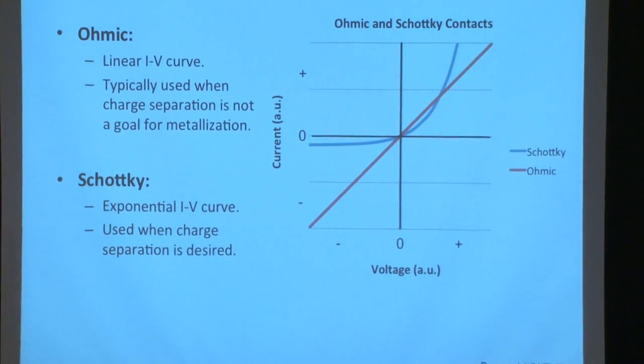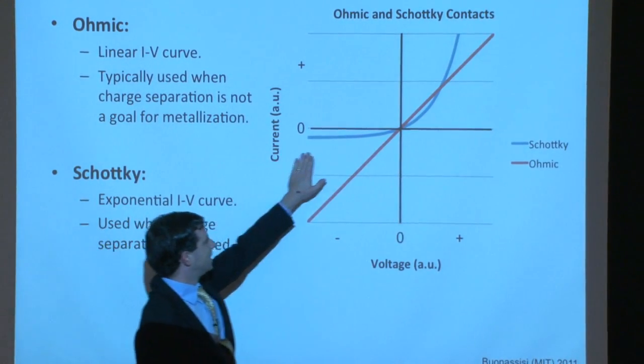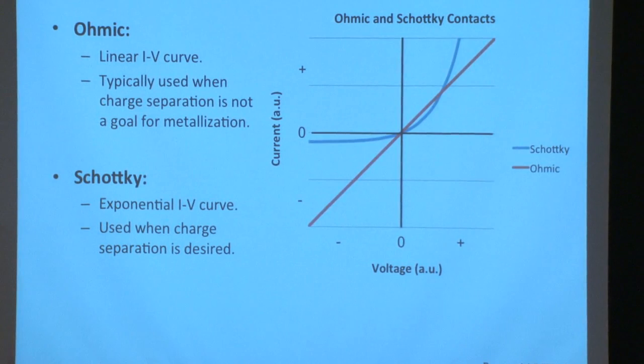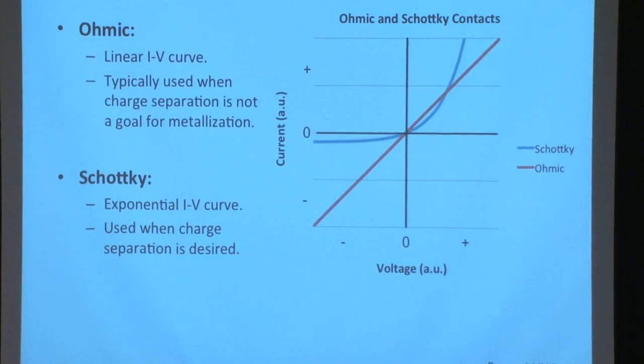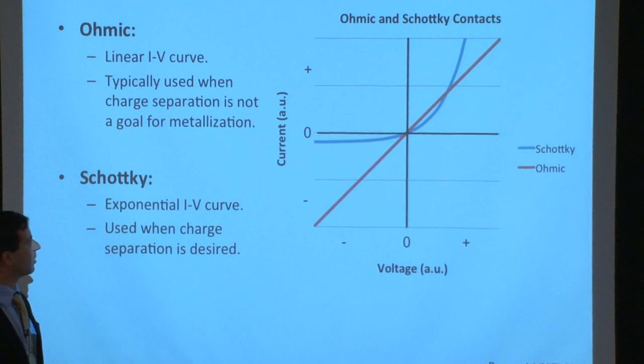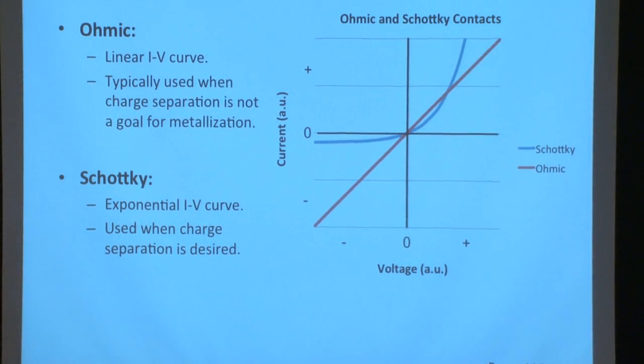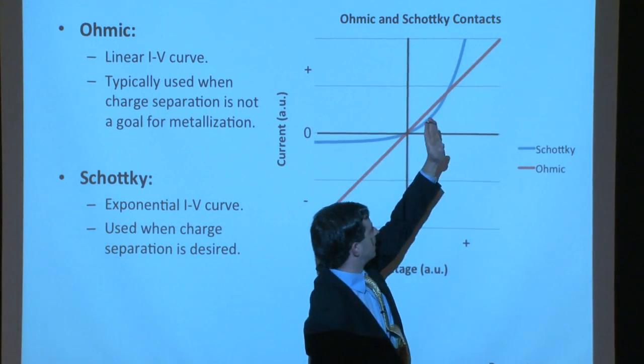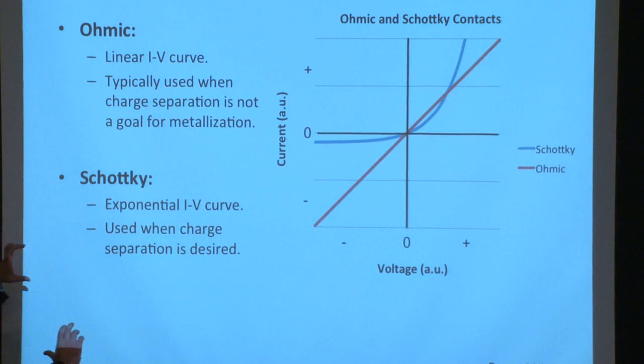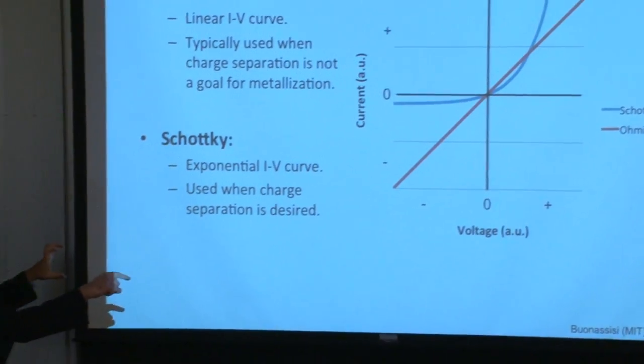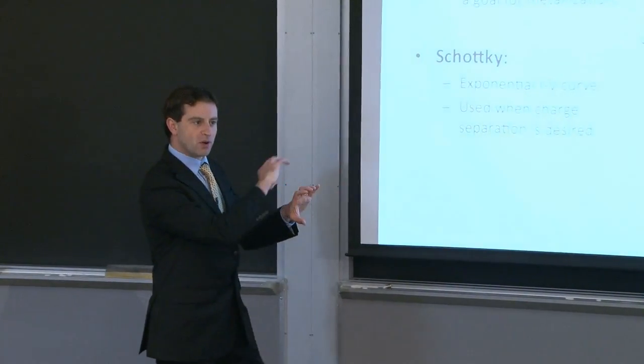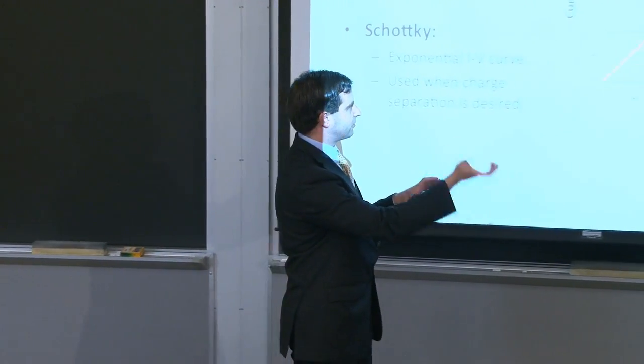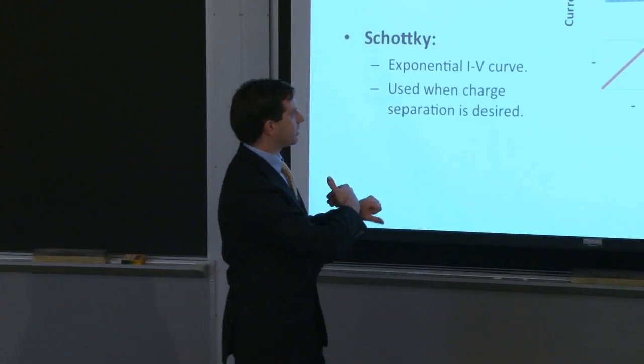A Schottky contact, on the other hand, follows this beautiful exponential curve that we've come to know and love from our ideal diode equation. As a matter of fact, it follows that same expression rather nicely. There's an exponential relation between voltage and current. So whenever we have an exponential relation between voltage and current, now that we know how a p-n junction works, and we recall that it's really that diffusion current that's driving the forward current right here under forward bias conditions, we've learned that when the barrier is too large, the electrons just can't make it over. But as the barrier begins dropping, an exponentially increasing number of electrons can jump over that barrier and move from the region of high concentration to the region of low concentration, or from the N-type material to the P-type material.